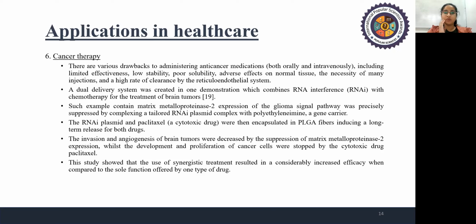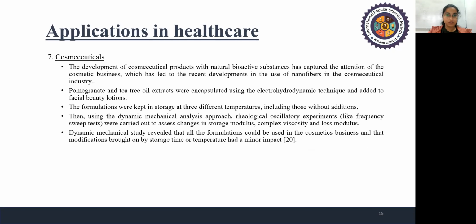Invasion and angiogenesis of the brain tumor were decreased by the suppression of matrix metalloproteinase 2 expression, while the growth and proliferation of cancer cells was stopped by the cytotoxic drug paclitaxel. The study showed that the use of synergistic treatment resulted in a considerable increase in efficacy when compared with the individual drug. Another, I'm going to deal with the cosmeceutical part of healthcare.